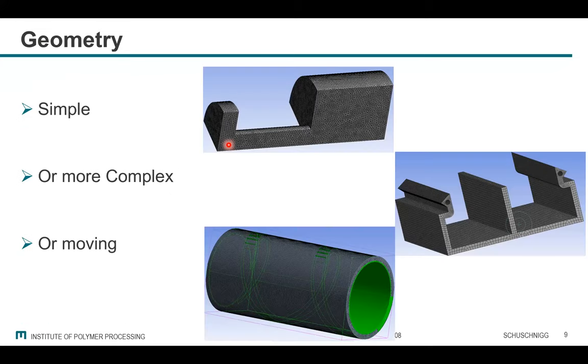I have here three different geometries. The first geometry is a quarter part of our additive manufacturing die, where we have our filament diameter of 1.75 millimeter. Here we have our die itself with 0.4 millimeter, and 0.4 millimeter as the height at the build platform or at the layer below. Then I can simulate the pressure losses in this case. In another simulation, I did a very similar setup where I wanted to calculate the temperatures.